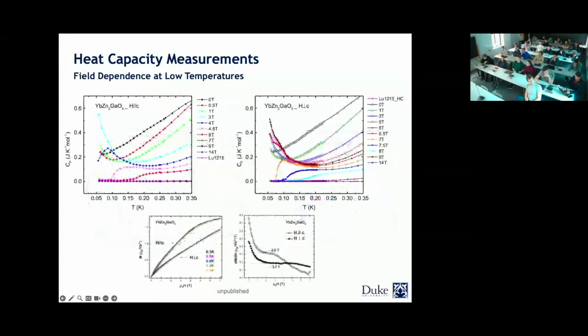Okay. So far so good, and so for this range in field and temperature, we think that we do have the Dirac quantum spin liquid candidate. However, something more interesting happened when we went to very high fields. Here you're looking at H perpendicular to C and H parallel to C, and this is the raw data. Up to 3 Tesla they are going up, and then they start to change behavior when we pass 4 Tesla. For H perpendicular to C, they are still going up to about 6, and when we pass that, they start to change their behavior.